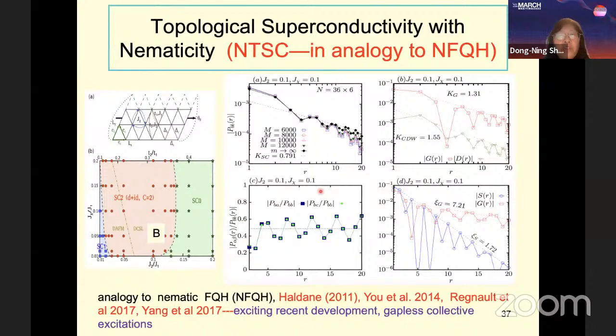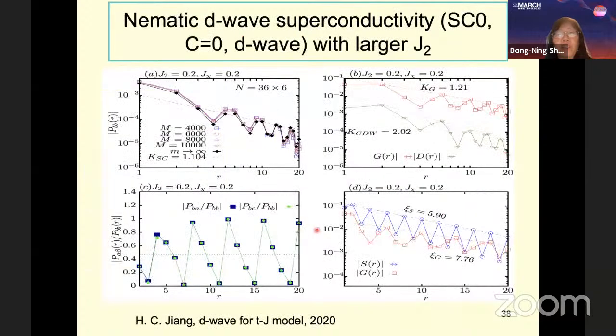But if we go to the larger J2 over J1 region, which has this D-wave phase, then the pairing is much stronger along this direction, the B direction. In the other two bonds, the pairing is weaker. The ratio between them is around 0.5. So it's a nematic superconducting phase.